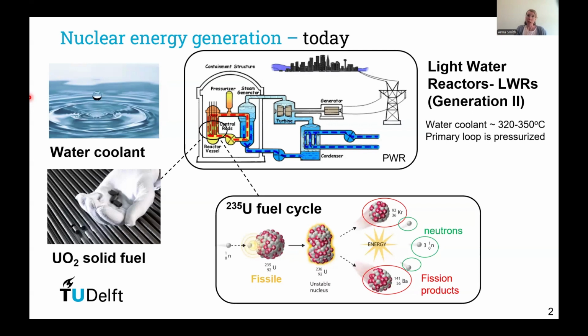Nowadays, nuclear energy is generated around the world by light water reactors, which are so-called generation 2 reactors, which run on a solid fuel. It's uranium dioxide, a ceramic, and this fuel is cooled down by water, which operates at a temperature of around 320 to 350 degrees Celsius, meaning that the primary loop has to be pressurized. The energy from the nuclear reaction comes from the fission of the uranium-235, which, when it undergoes fission, produces fission products, a few more neutrons, and a lot of energy.